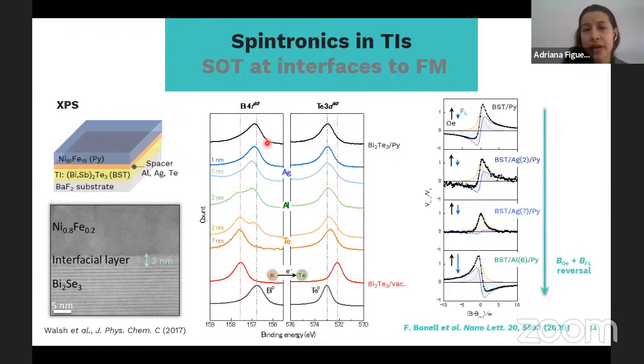But then when we have the bismuth telluride with permalloy, without any interlayer in between, these peaks move towards those of the single atom, which is not what you want. You want to recover the position of the alloy, and we can do that by adding an interface. For example, if we add a layer of tellurium, we manage to recover those positions, that chemical state of the tellurium and bismuth, which means that when you have this interface with permalloy, the interface becomes poor in tellurium.